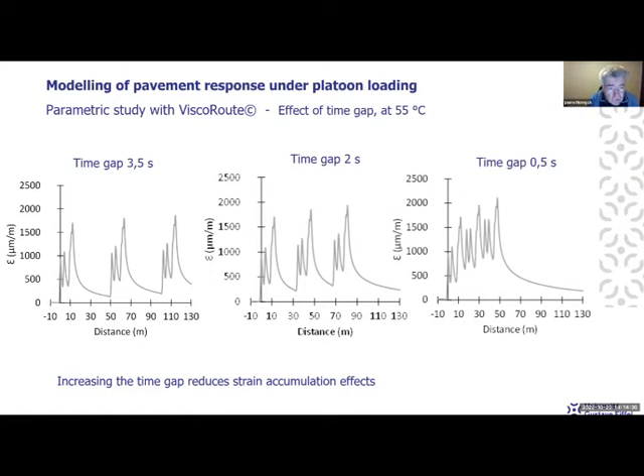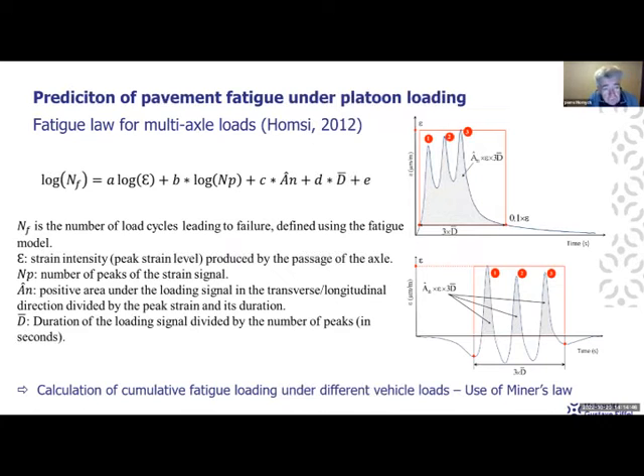So ViscoRoute, when it is calibrated on the results of the experiment, can be used to predict the effect of different track configurations and to optimize the track configurations to reduce the impact on the pavement. And then we also tried to predict the fatigue behavior under platoon loading.